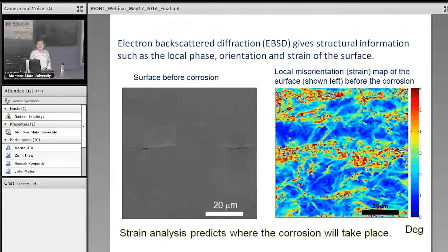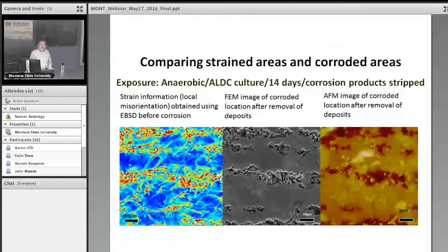Somebody got a thesis out of that. And here it is. You can see wherever there was red, this is the same area after several weeks of corrosion, matching one-to-one. And this is an atomic force microscope image of the same area. We can tell the depths of these, and we can actually calculate the rate, compare it, and within 4 or 5% accuracy, it was identical. That's the power of analysis.